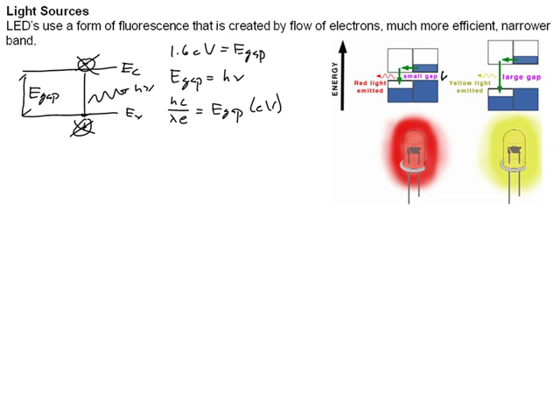Given Planck's constant, 6.62 times 10 to the minus 34, the speed of light, the wavelength, and the charge on an electron, from the gap of a semiconductor or LED, you can calculate what the wavelength or color of light that comes out is. For a red LED, you have a fairly small band gap right here, and you have a junction of N-type material that has extra electrons, and P-type material that has extra holes. The recombination of these carriers takes place in the depletion region of the diode, and the small band gap emits red light. If you have a semiconductor material with a larger band gap, you would get shorter wavelength or more energetic light. A larger band gap still would give you green, and still a larger band gap would give you blue.